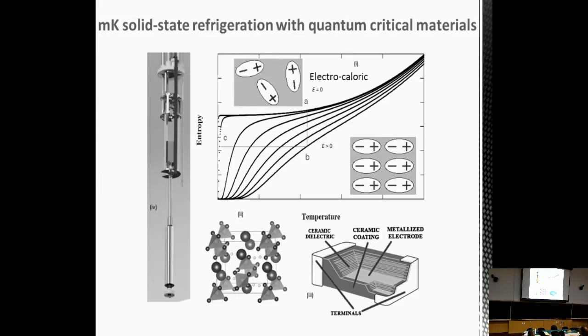So these ferroelectric materials at low temperature have an electrocaloric effect like this, where you can apply an electric field to a disordered material. You do that isothermally, and the dipoles line up. And then you isolate your experimental system and the refrigerant from the rest of the world, and you sweep down the electric field adiabatically, and then you have to go back to this curve, and the only way to do that is to lower the temperature. And so we're now making these into millikelvin solid-state refrigerants.